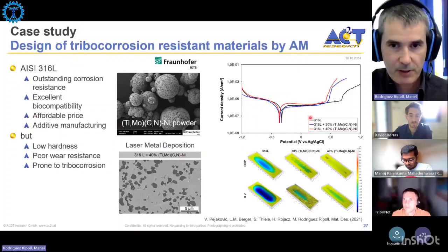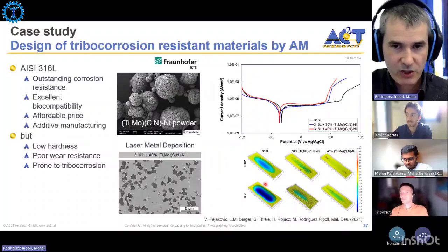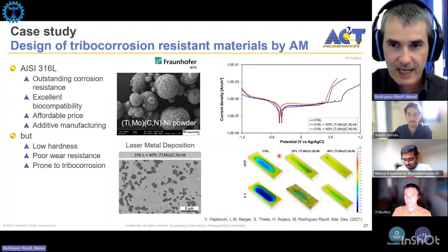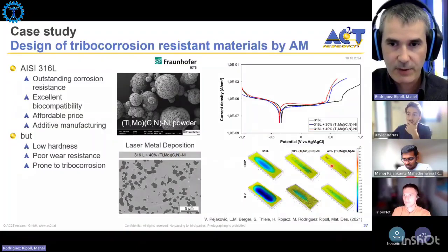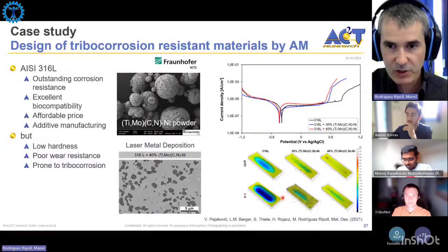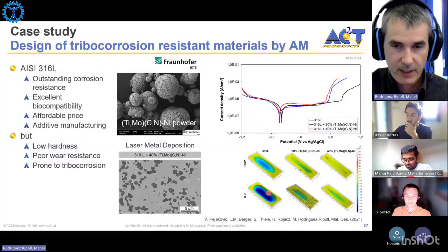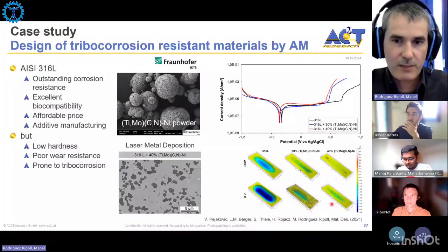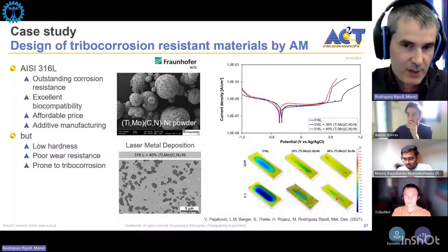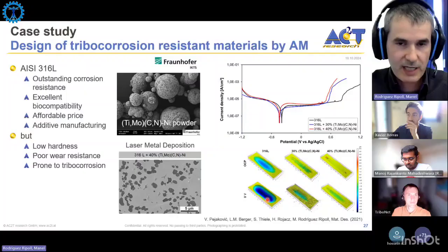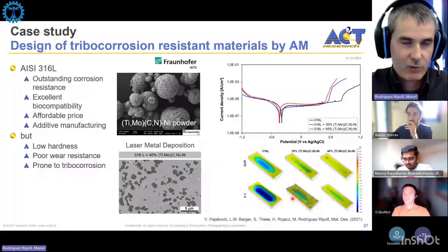And I'm showing here, for example, the wear scars after the tribocorrosion experiments. These are OCP, so we didn't do anything, just following the potential as it was established automatically, spontaneously. And you see that with increasing concentration of titanium carbonitride, the tribocorrosive wear volume gets smaller for higher concentrations of titanium carbonitride. This is even true if you apply a passive potential, even though if you compare passive potential with OCP, you see what we saw before, that under an applied passive potential, the wear in general is larger, but even under these more detrimental conditions, the material performs much better when compared to the unreinforced 316L.